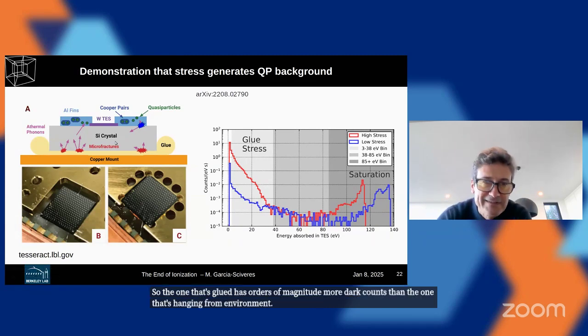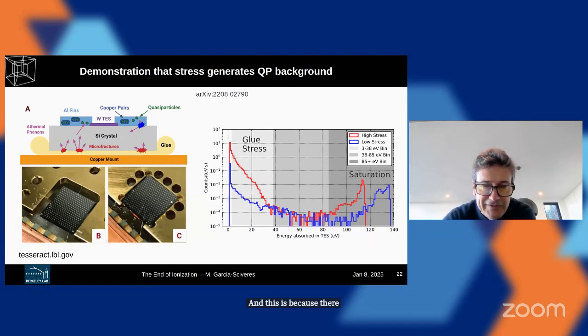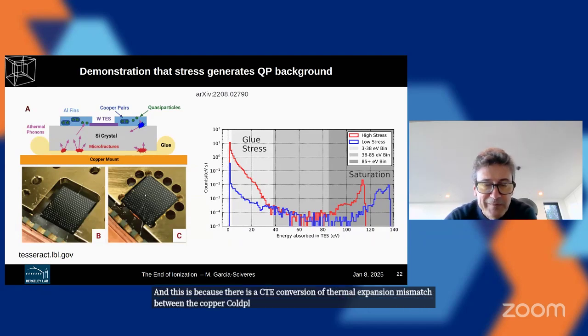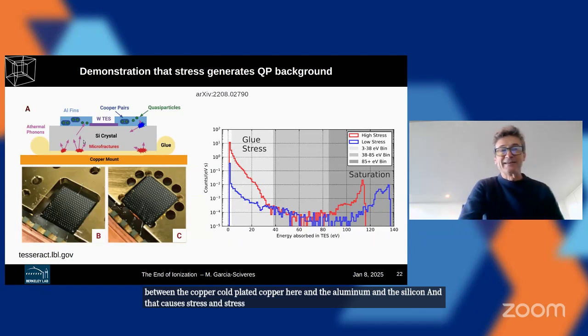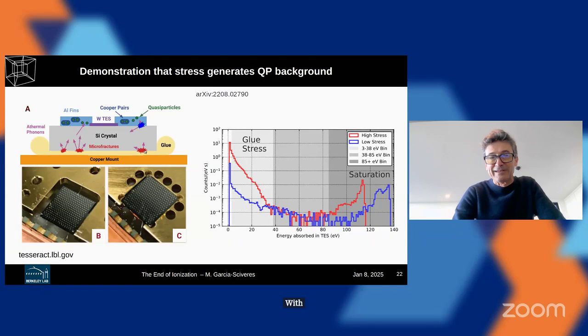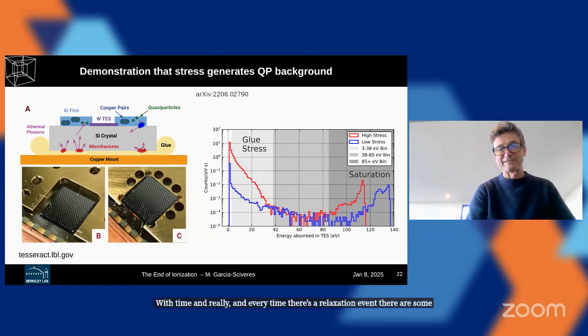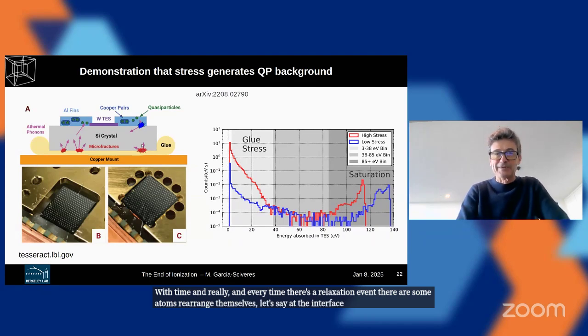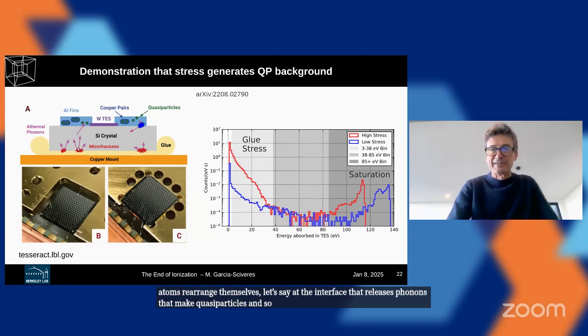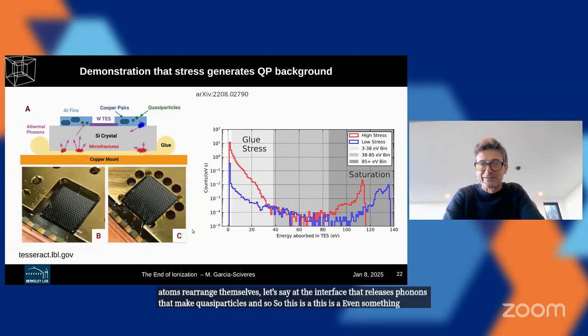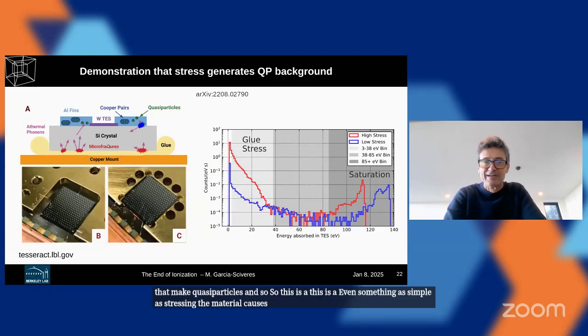And this is because there is a CTE, coefficient of thermal expansion, mismatch between the gold-plated copper here and the aluminum and the silicon, and that causes stress. And stress essentially relaxes with time, and every time there's a relaxation event, some atoms rearrange themselves, let's say at the interface, that releases phonons that make quasi-particles, etc. So even something as simple as stress in the material causes a huge background to these quasi-particle detectors.